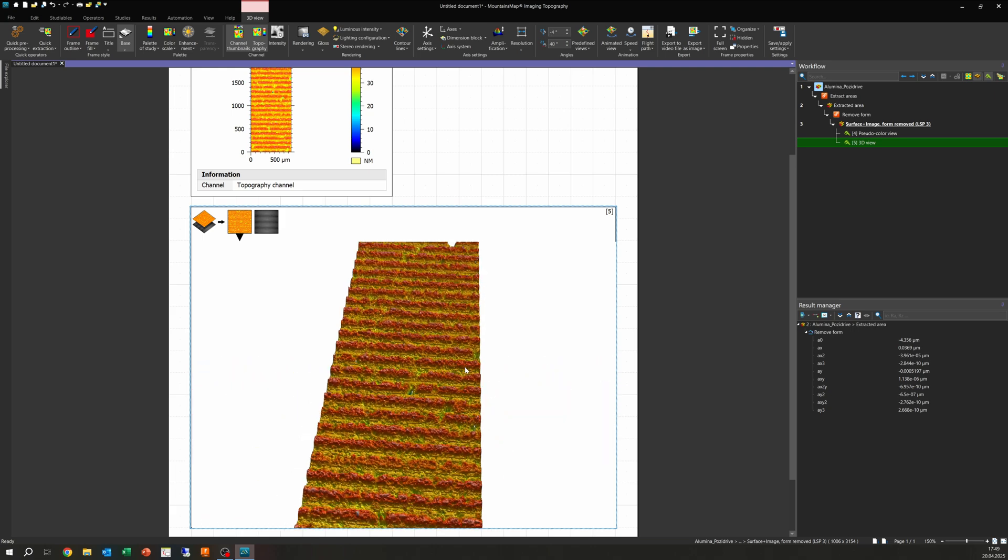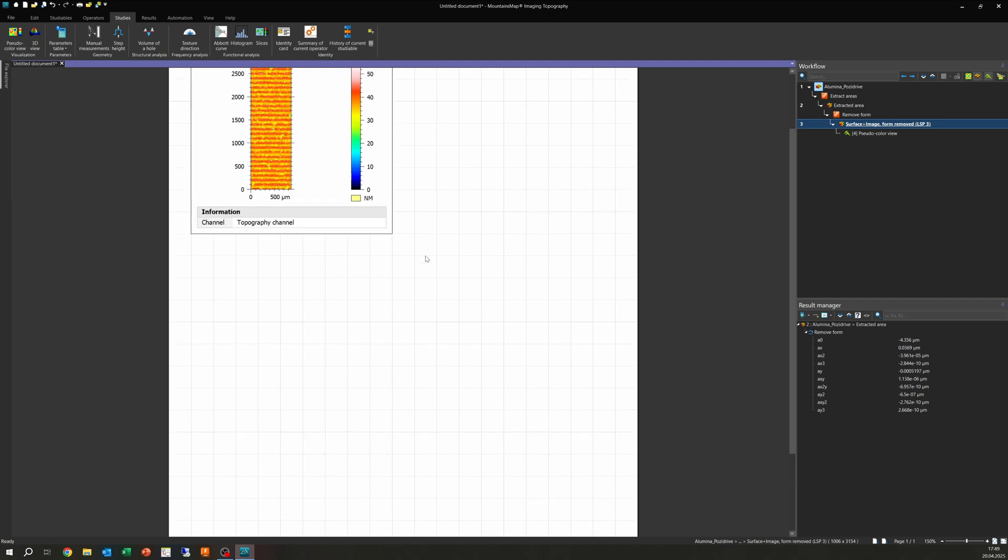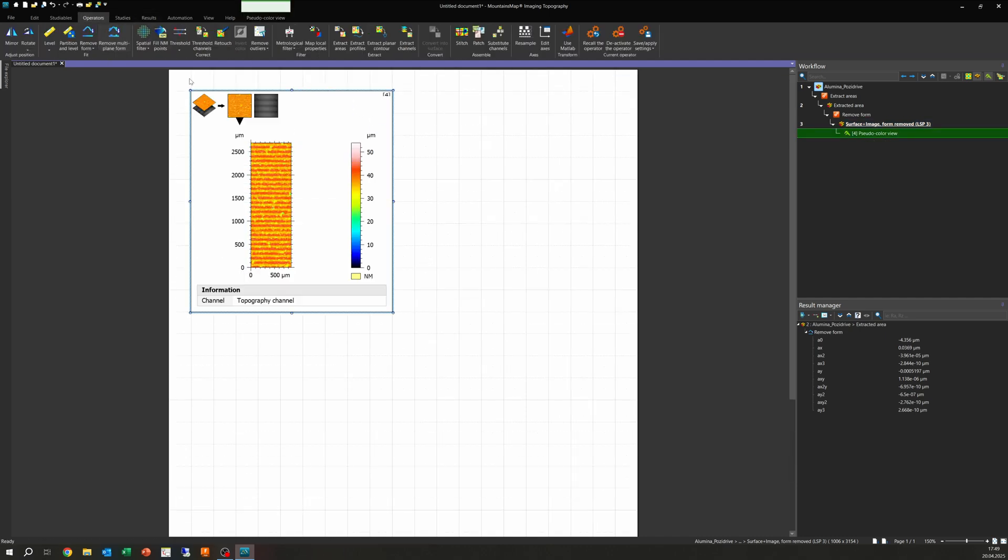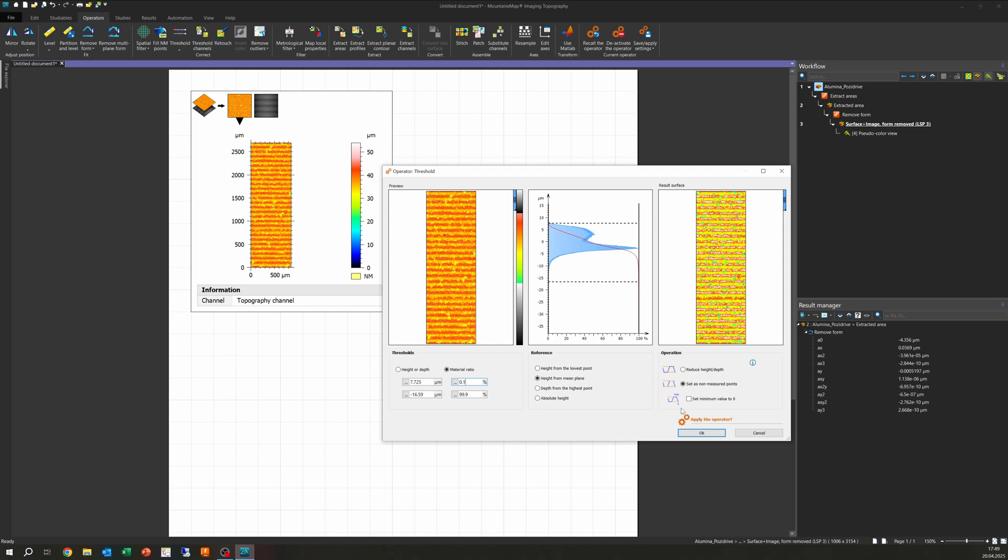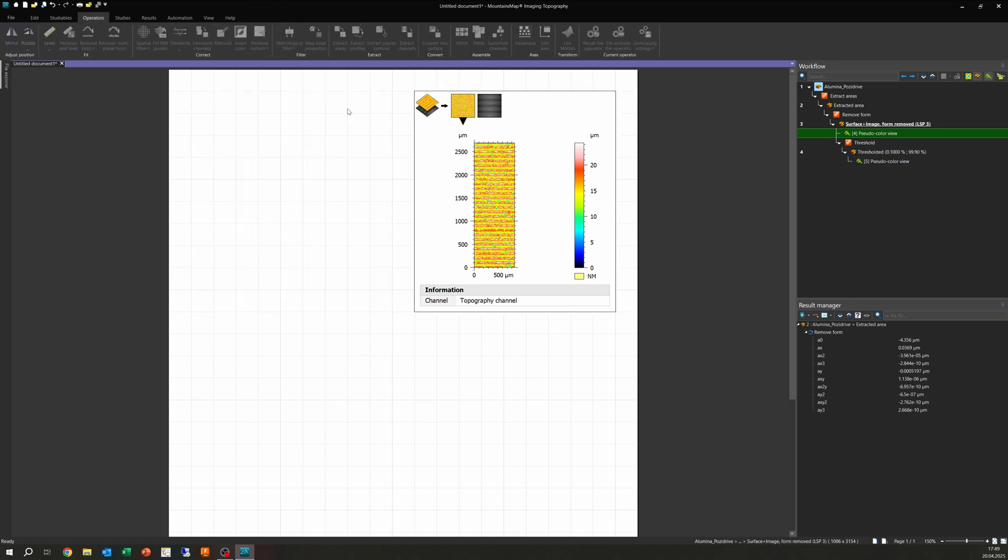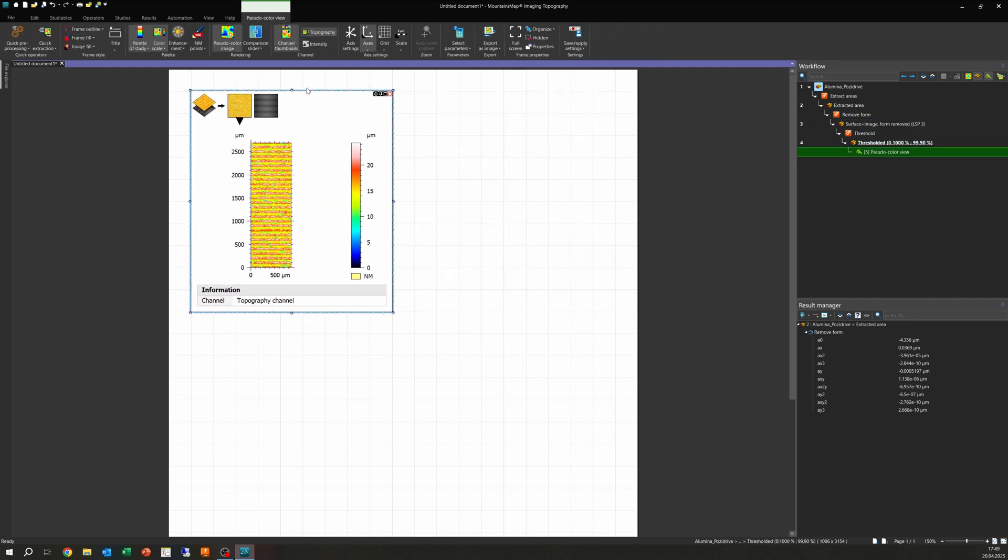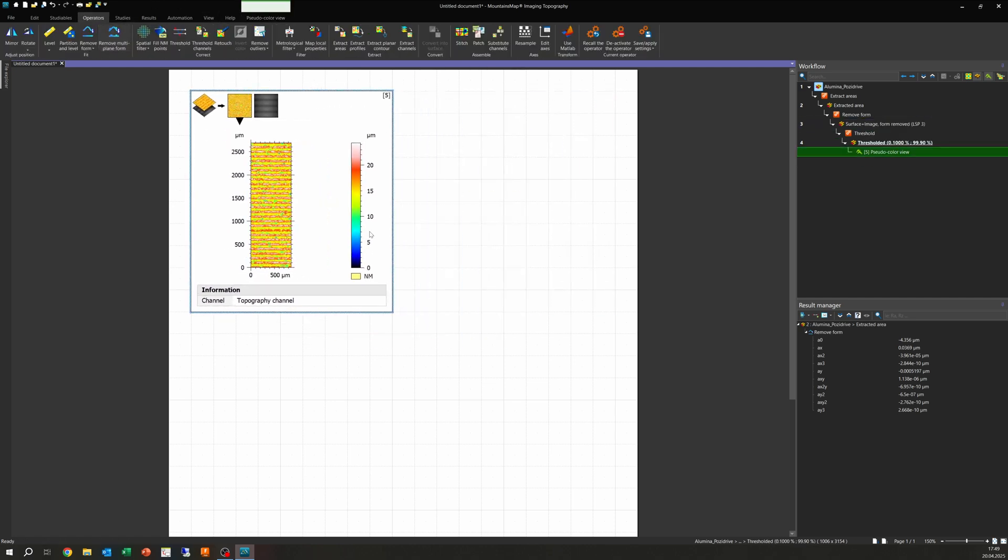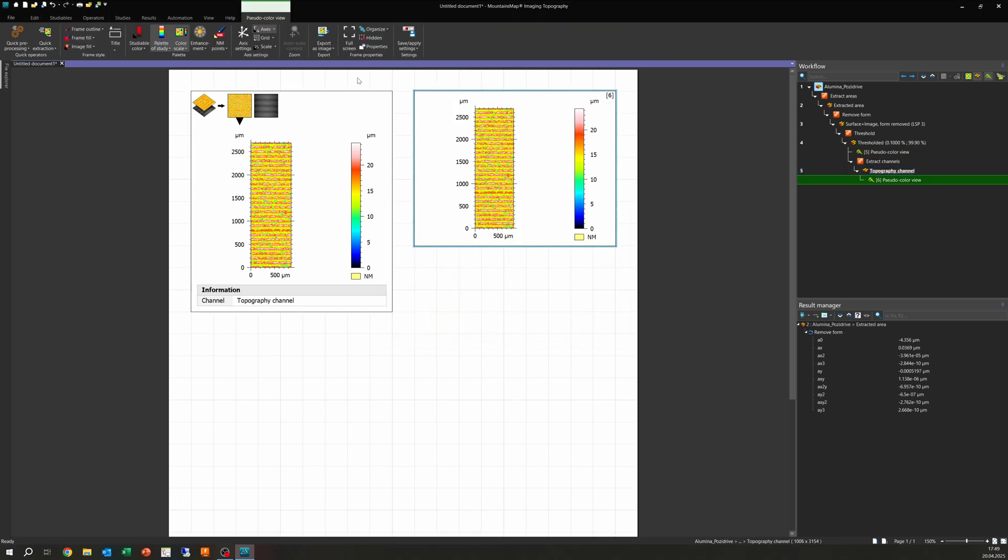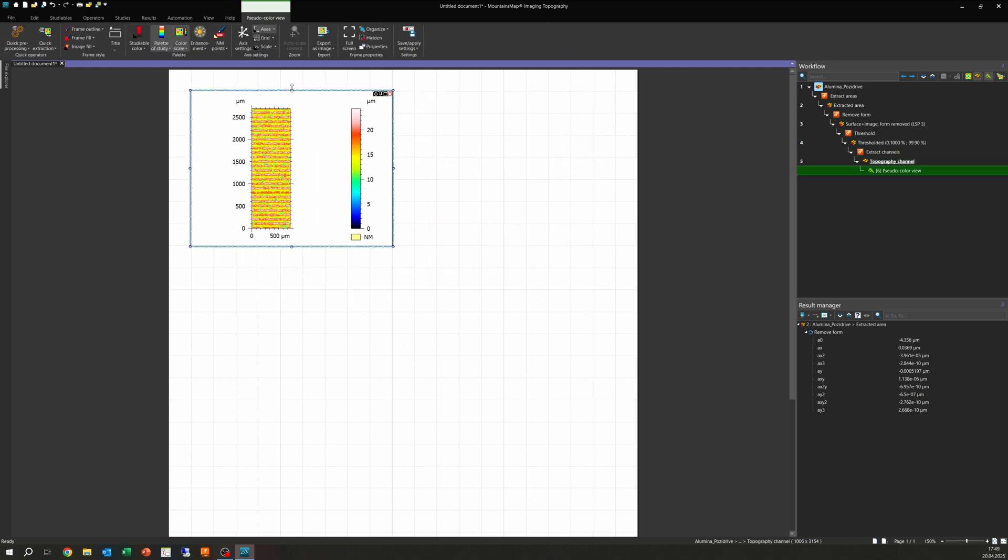Our next step will remove these outliers you can see here. For this, we're going to apply a threshold. A threshold basically cuts off something from the data. We're going to take a minuscule amount here, cutting off the uppermost and lowermost 0.1%. Because we cut off some areas, we are now left with some voids. To have a nicer visualization, we're going to have the software fill these areas of non-measured points. It doesn't really change anything on the result, as a smooth shape is chosen to fill these, and I've limited to less than 50 points, but it will make it easier to look at profiles later.